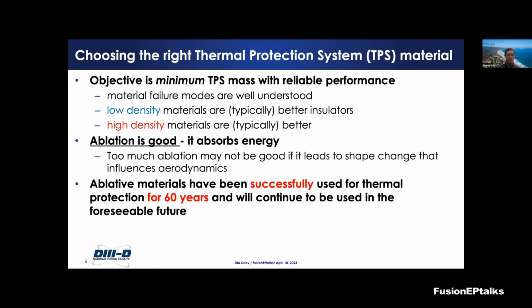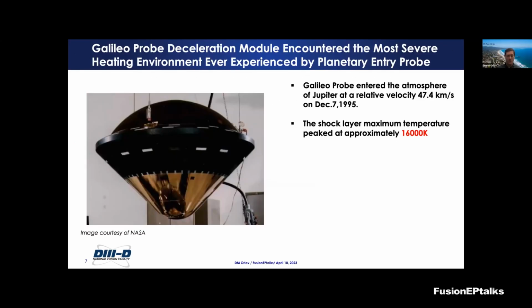But ablation is probably the best process that we have to remove the heat now when the spacecraft enter other planets' atmospheres. So here I'm focusing on one particular spacecraft, and this one is the Galileo's probe, which was sent to Jupiter many, many years ago. The probe entered Jupiter's atmosphere on December 7th, 1995, at a relative velocity of almost 50 kilometers a second, 47.4 to be exact. The temperatures at the shock layer were approximately 16,000 kelvins.